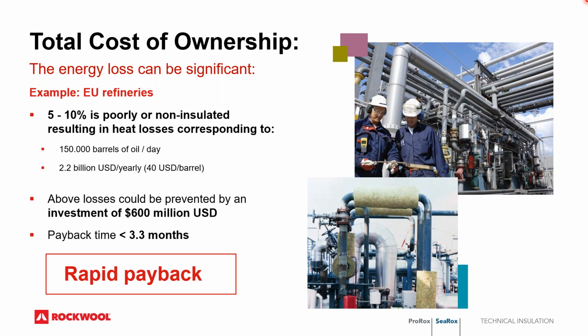Let's look at refineries in Europe. Approximately 5 to 10% are either poorly insulated or not insulated at all, which results in heat losses corresponding to, this is a lot, 150,000 barrels of oil per day. And if we just take a cost of even $40 per barrel, that translates into $2.2 billion a year of loss. These losses could be prevented with a simple investment of $600 million.